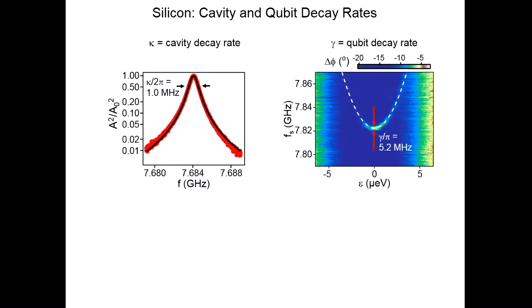Now we want to compare that to the loss rate through the cavity. We can directly measure that from the quality factor of our cavity. This device has a loss rate that's about 1 megahertz. It's good, it's less than our coherent interaction rate. And then we can also measure the line width of our atomic transition. And this was a surprise because 5 or 6 years ago we tried to do this in different devices made out of indium arsenide, and the line width was very broad. It was about 1 gigahertz or a few hundred megahertz. There's really no chance of getting into this coherent regime.